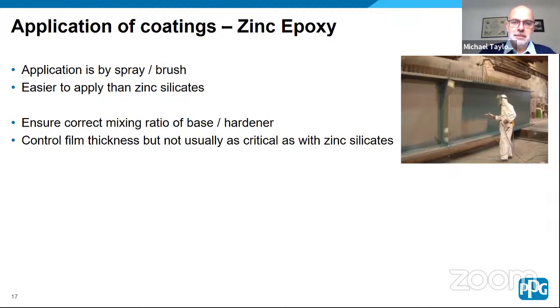But bear in mind that these zinc coatings are highly pigmented and not cohesively as strong as some other coatings. So if you apply a very high build epoxy coating over a zinc coating, you can find the stress as the epoxy coating cures can break cohesively within the film of the zinc coating. So that's another good reason to keep the coating application tightly controlled.